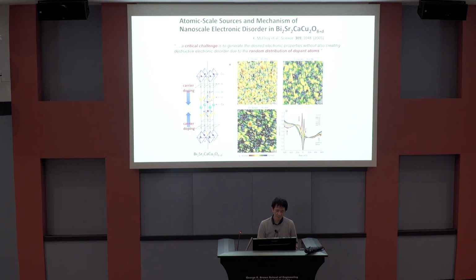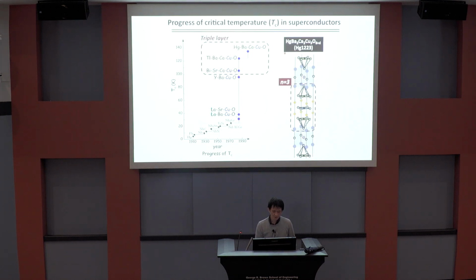So it is kind of challenging to observe the intrinsic electronic state without random distribution of dopant atoms. You cannot forget that the highest TC is achieved in the triple layer, which has an inner layer that is very clean. So it is very important to study the electronic structure and electronic property of this clean inner layer.